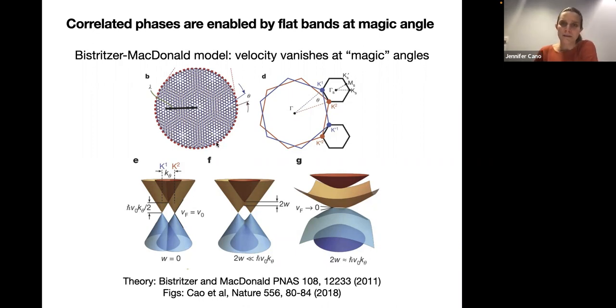Bistritzer and MacDonald came up with this simple model, which is that all of the low energy physics in graphene, a single layer of graphene, happens at the Dirac cones. And so if we have two layers of graphene, then we should consider how these two Dirac cones in the two different layers talk to each other. So this picture is meant to show the K points in graphene. Each one of these has a Dirac cone, which you can see like this. And these Dirac cones will overlap with each other.